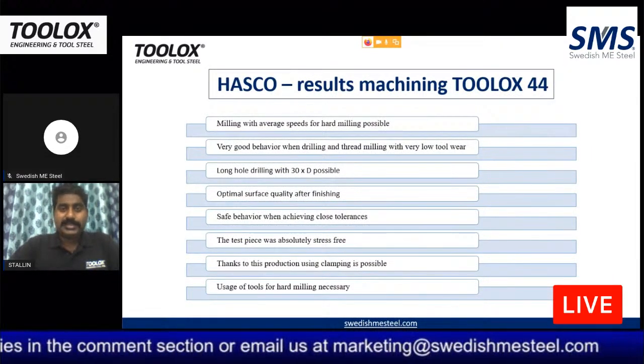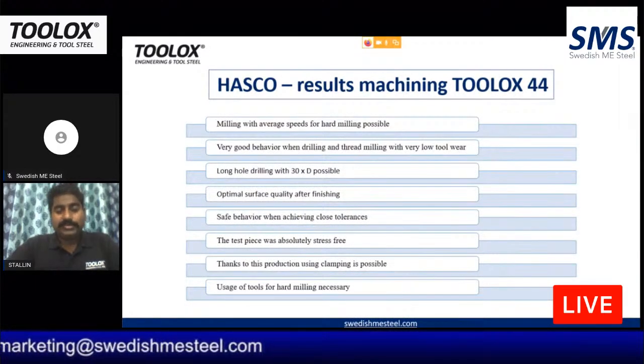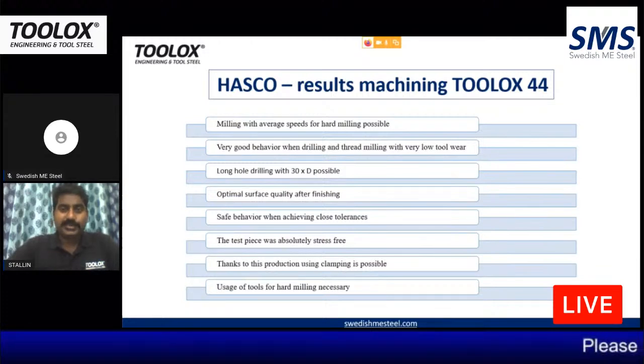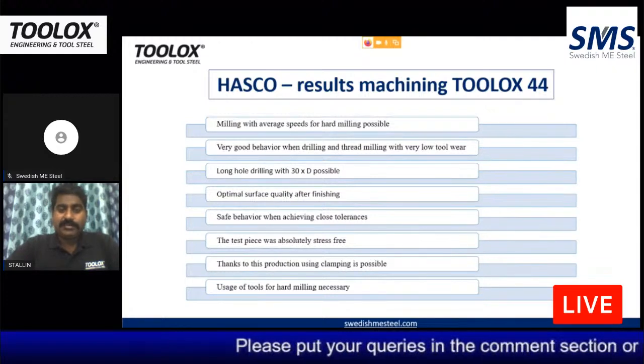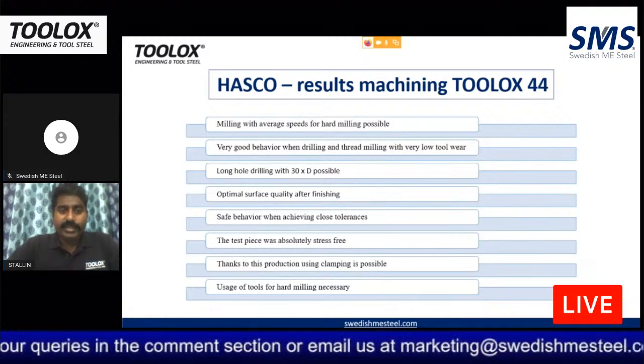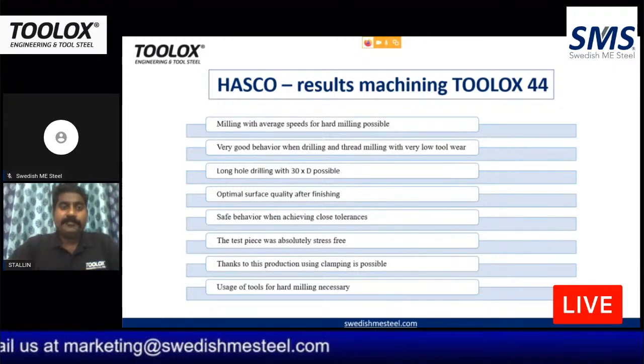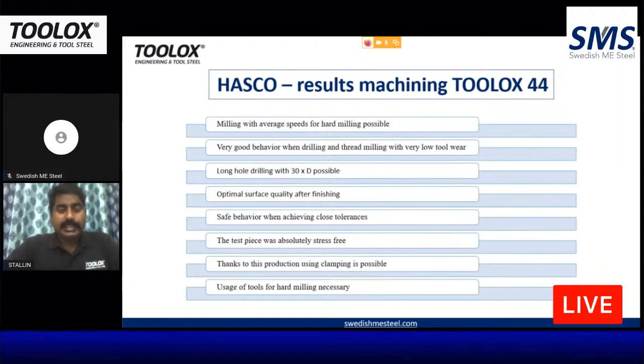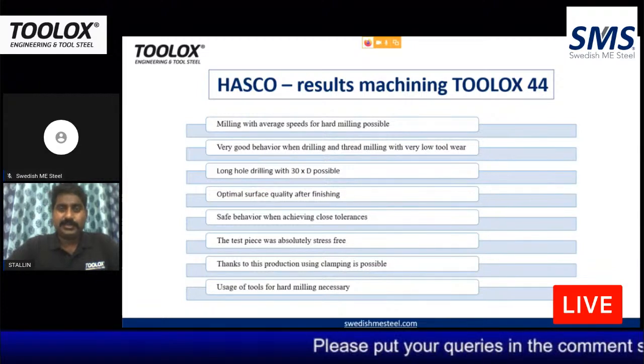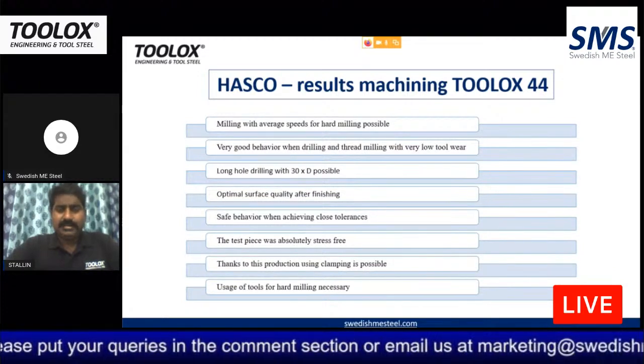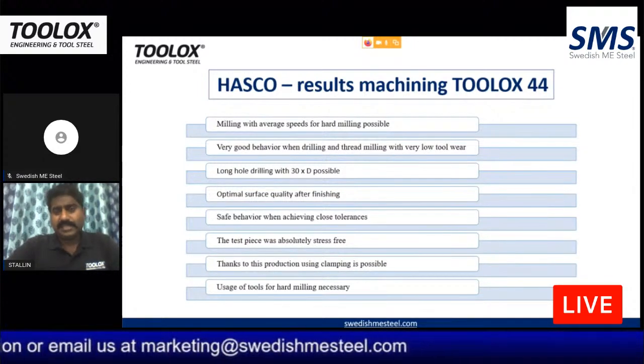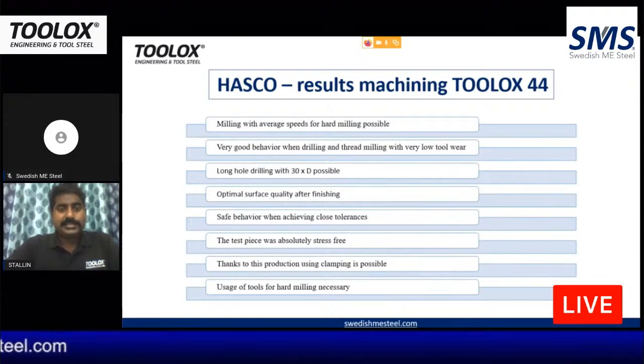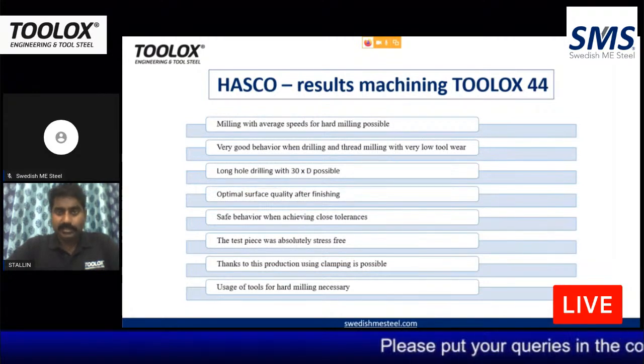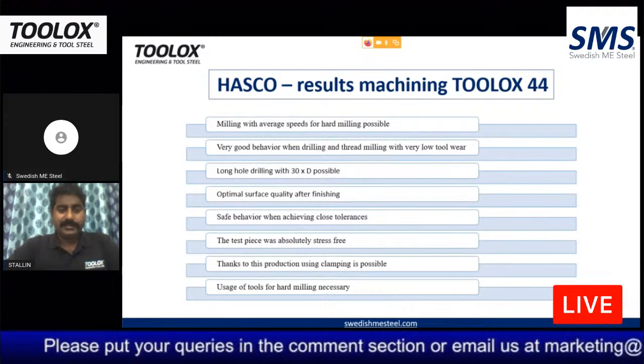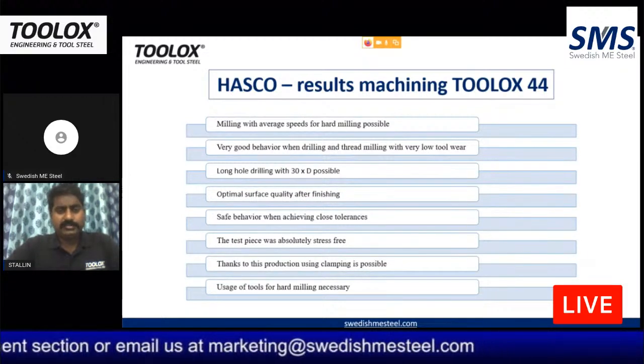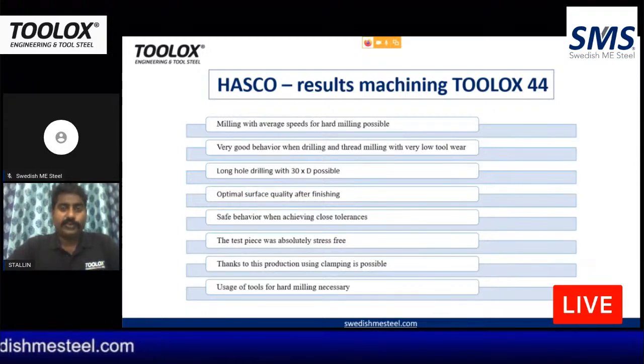Adding to the Toolox 33 test pieces which they have done, Hasco has also done machining on Toolox 44. Let's see some of the comments they have mentioned. Milling with average speeds for hard milling is possible. Yes, there is some very good behavior. When they drilled and did thread milling with Toolox, they were able to do it with relatively low tool wear. Long hole drilling is also possible, 30 x D. They got absolutely fantastic results on the surface quality of the plate. And as we already discussed, this test piece was absolutely stress free since there are no internal stresses in the material. So these are some of their observations of machining Toolox 45 HRC material.